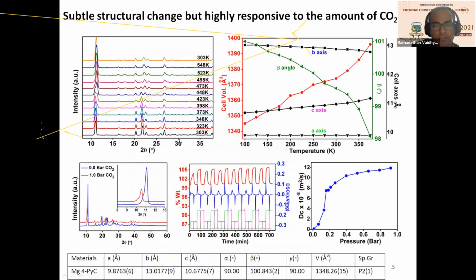Okay. Now, I am trying to see, is this openness that is coming in due to CO2 partial pressure because of a structural change? And I am measuring a variable temperature XRD of this sample. And from that, I am looking at the trends that the lattice parameters are showing. I am seeing that the a axis does not change much, the b axis does not change much, the c axis is also not changing much, but the unit cell volume shows reasonable change. And most importantly, the monoclinic angle is showing a good change. The structure parameters are given here for this magnesium isonicotinate MOF. You can see it is a monoclinic P21 space group, and beta is non-90, others are 90. So this is the beta angle. I am showing you that it is changing continuously as I increase the temperature. So there is no major structural change. If there were a major structural change, the entire lattice parameter would change, as I already showed you.